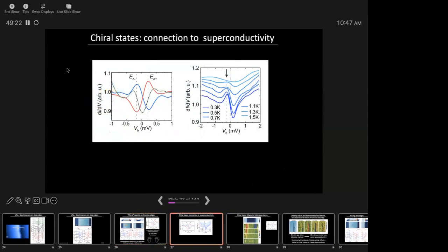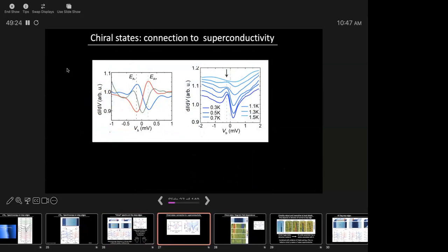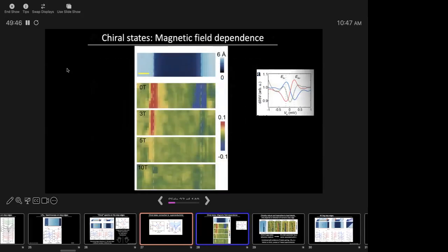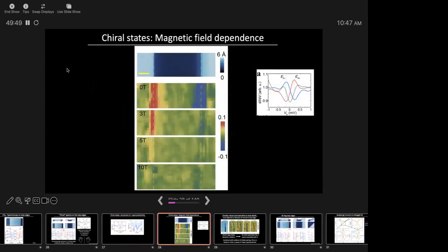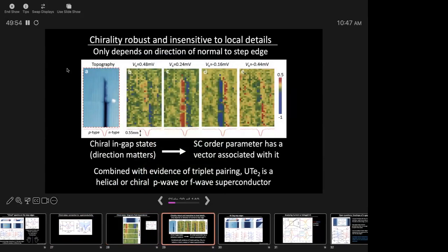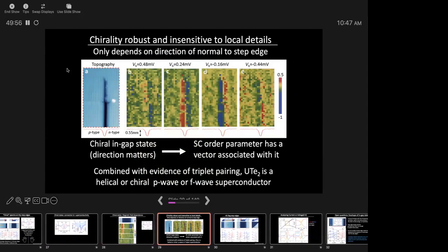So then, this is just quickly to show you, because I have to show you the charge density wave. Yes? How do I understand the step? There is the uranium ditelluride on both sides, but there is a unit cell, so it's one more layer above. Correct. So this feature disappears at Tc. It disappears with magnetic field, exactly where superconductivity is highly suppressed. So it has all the hallmarks of being associated with superconductivity.